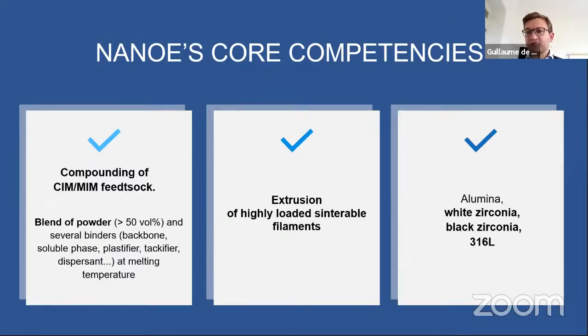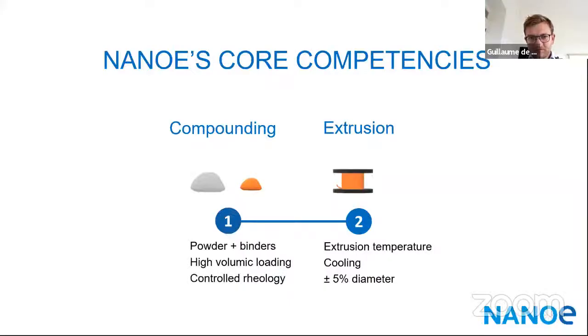We mix a few different thermoplastic binders with a lot of ceramic or metal powder to get to very high loadings of powders. These feedstocks can be used for injection molding, but they can also be extruded into highly loaded filaments. And that makes filaments available in alumina, zirconia, and also in stainless steel. Just an explanation of that. So the compounding phase is where we will mix the powder and the binder, and extrusion is what will give us the filament. So that's really what we are good at.